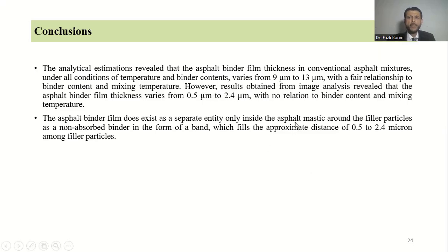However, results obtained from image analysis reveal that the asphalt binder film thickness varies from 0.5 micrometer to 2.4 micrometer with no relation to binder content and mixing temperature. While looking at analytical values, the film thickness varies from 9 micrometer to 13 micrometer with a strong association to binder content and temperature. But the film thickness measured using SEM ranges from 0.5 micrometer to 2.4 micrometer with no relation to binder content and mixing temperature.